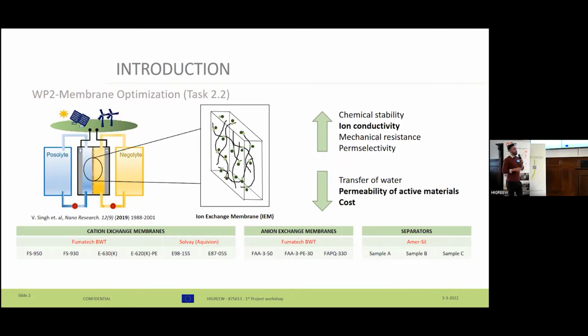So we were required to evaluate different commercial materials, such as cationic and anionic ion exchange membranes and porous separators from companies such as Fumatech, Solvay, and Amersil. Depending on the active material, we will deal with cation or anion. In the case of porous separators, I have to say that they were evaluated because they are cost effective and they possess very high ion conductivity, but the mean pore size is extremely large, so the permeation of the active species will be so dramatic that they were difficult to work with, so they were discarded. And for the rest of the materials, some fundamental parameters were considered, such as the ion exchange capacity, the ability to absorb water of these materials, the resistivity, and the permselectivity.